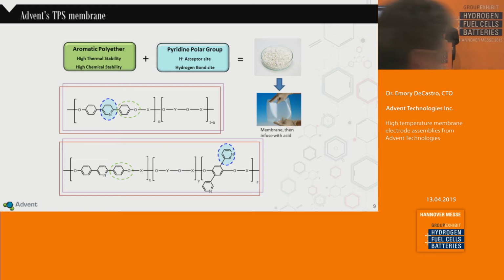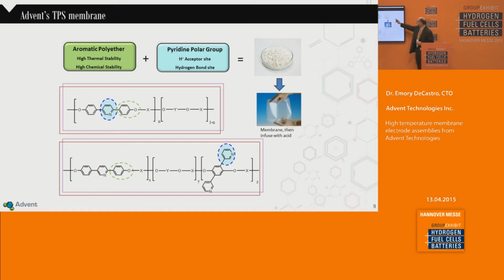The TPS membrane gets its stability primarily through this aromatic polyether bond shown in the upper part. This gives us thermal stability, chemical stability. To that polymer, we actually add a pyridine group. It's this pyridine group that becomes the proton acceptor, basically a wick for the phosphoric acid, and keeps it trapped within the membrane. At Advent, we actually make this polymer, it comes out as a powder, we process that into a membrane, and then imbibe that membrane with phosphoric acid.